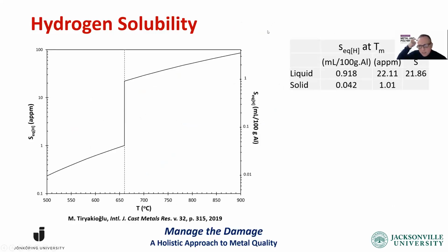When we calculate, and we have this weird unit, milliliters per 100 grams of aluminum, I converted that to atomic ppm for your information. So for 1 million aluminum atoms, we're talking about 22 hydrogen atoms in liquid, and 1 in solid. And again, we're talking about pure aluminum. So when we look at what I call the supersaturation, if we immediately go from liquid to solid, that's about 22. So what does that mean? That drop is 22. I divide liquid solubility by solid solubility.